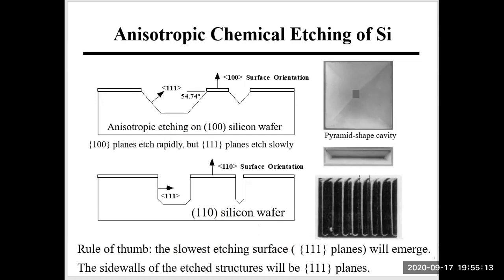Then the side walls of the etched structures will be 111 planes. These two slanted side walls are 111 planes. The 4 side walls of this pyramid-shaped cavity are 111 planes, and these vertical side walls are 111 planes. So this is a simple rule to explain the anisotropic etching in single crystal silicon.